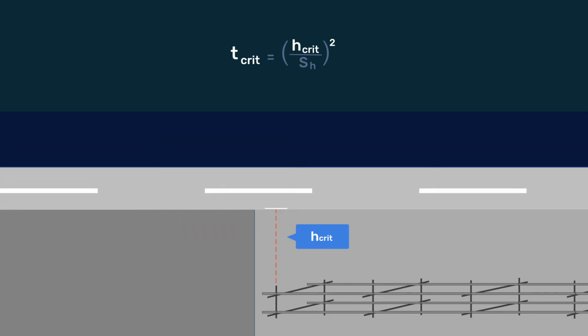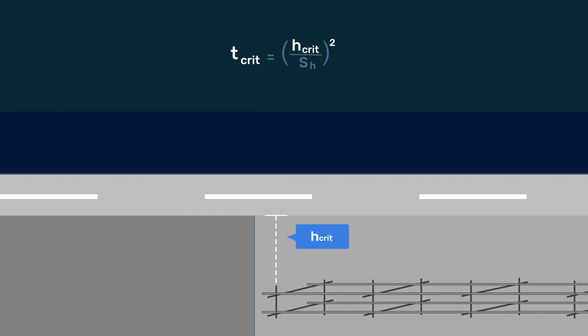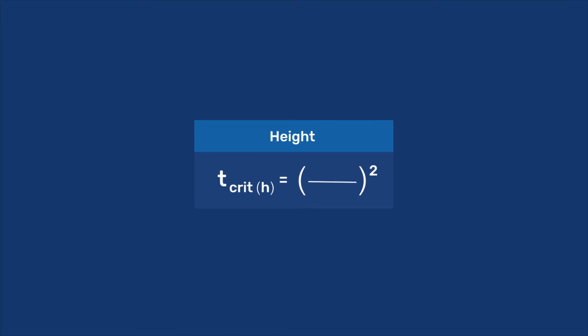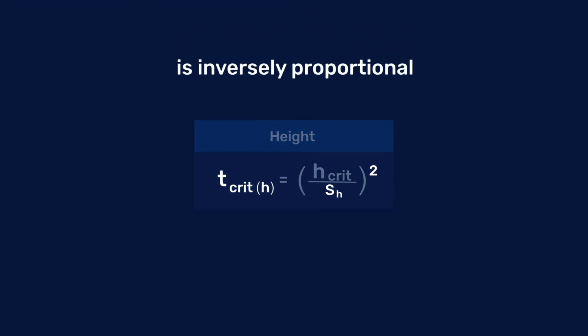Let us now consider situations where the object's dimensions cannot be changed, but the material can. For this, we examine the dependence of the critical time on sorptivity. Since the critical time is inversely proportional to the second power of sorptivity, decreasing that property can have an important beneficial impact on service life.